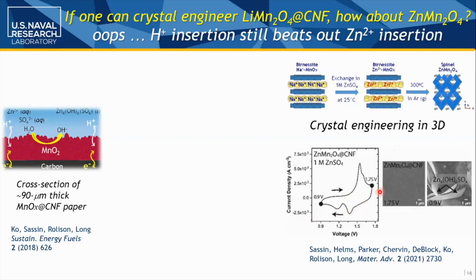So where you're here, where you've not done any zinc into or out of the system, if you've not discharged the battery, it looks like our classic nanofoam. But after we've taken it to 0.9 volts versus zinc, you see all of these precipitates, which is the proton insertion into the birnessite, shifting the pH, very basic at that electrified interface, and you precipitate a zinc hydroxysulfate. So it's never really been a zinc insertion. It's always been protonic based.